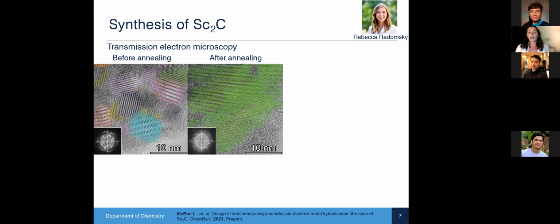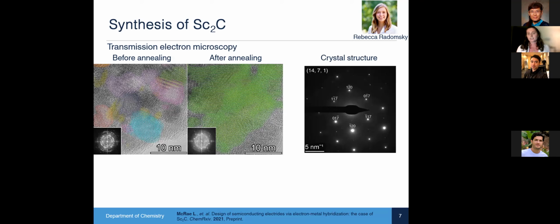So we took an electron diffraction pattern of this very large crystal in the after annealing photo, and we found at this zone axis that the 117 plane is present, and this plane actually aligns to the peak at 50 degrees that I pointed out in XRD that is unique to the layered phase. So what we're showing here is that this very large green crystal after annealing is in fact all layered, which again supports that after annealing, we were able to get much more of the layered phase and that we were able to favor the thermodynamic product.